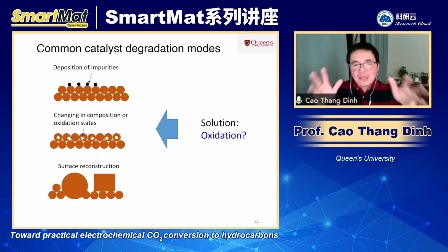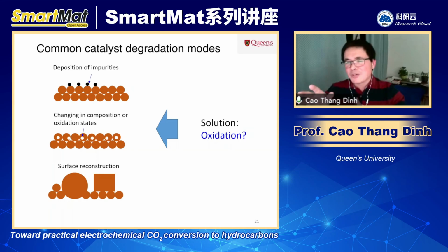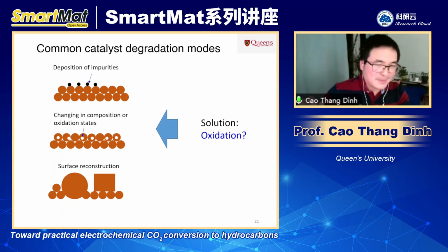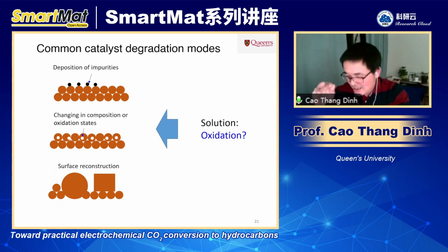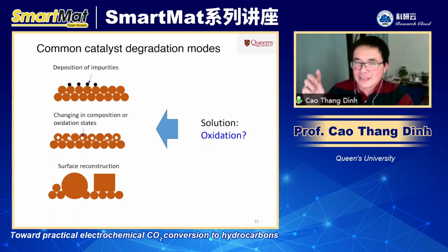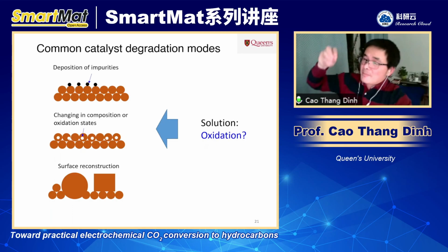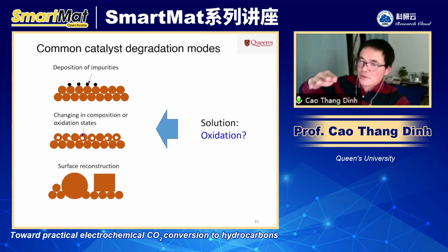Now, if you look at these three mechanisms and try to figure out whether there is any way to have one solution that can overcome all three of these problems, then you may think, okay, one simple way would be to try to oxidize the surface. Now, why is that? If you have a metallic deposit on the surface right there, if you can oxidize it back to the metal ion, it can go back to the solution.